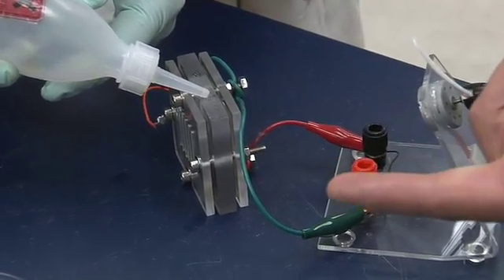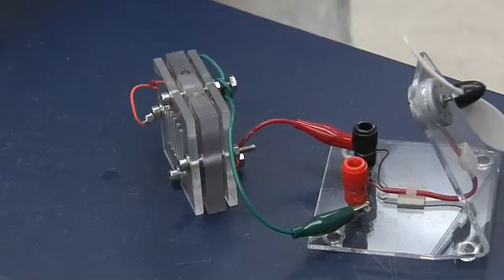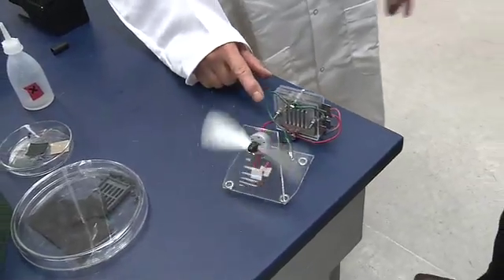These membrane electrode assemblies are the heart of all PEM-based, polymer electrolyte-based fuel cells. We made a whole bunch of these for the U.S. military. With just six or seven drops of methanol, we'll run this thing for about 11 hours — that's how long we've tested it. This is a very simple system: no pumps, no blowers, no external electricity. It's air-breathing — it just breathes air on one side, a little fuel on the other, and we have power.